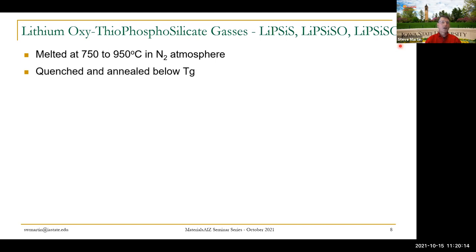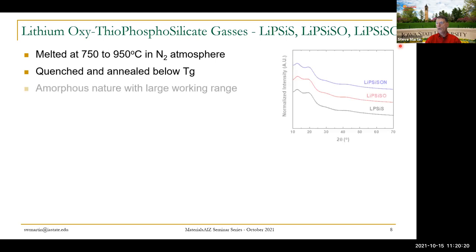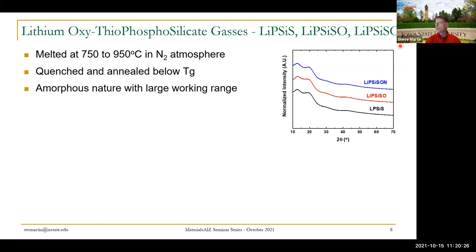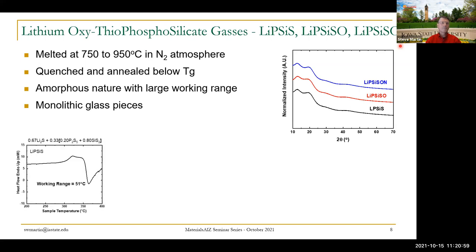These glasses are melted rather traditionally, but inside a glove box. They range in temperatures. They quench to below the glass transition temperature and anneal. And then, of course, we take X-ray powder patterns, and we see very little, if any, crystallization of these glasses. And we get monolithic glass pieces. We do this in two stages. Initially, we make small 3 or 4 gram samples, and then we do all the electrochemical, all the thermal testing on these small, relatively low cost samples, and then we pick an optimized composition and scale that up. And I'll talk about that. But let's talk about the small scale work where we're just proof testing, as it were, the glasses.